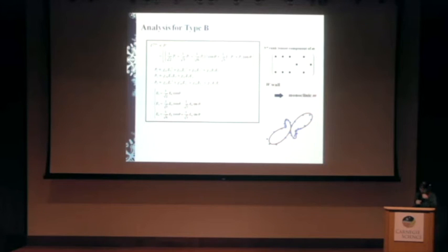And we also did a polarization analysis to determine the symmetry of the domain boundary. In the case of the type B domain boundary, it can be fit with a monoclinic M. And this symmetry belongs to the polar group. So we can conclude that the domain boundary of calcium titanate is polar.